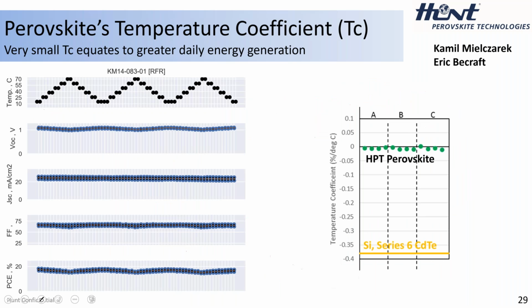In this case here, we take a similar setup and we can actually modulate the temperature over time, as you can see here on the top curve. And what happens? So we start from 10 Celsius and heat to 70 Celsius. Now, if we were silicon, or as is published in the Series 6 data sheet online, you would see a significant drop in power, something of this very exaggerated nature. It's not that low, but there would be a significant drop in power as the system were to heat.